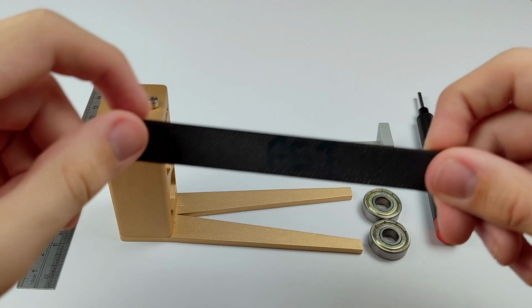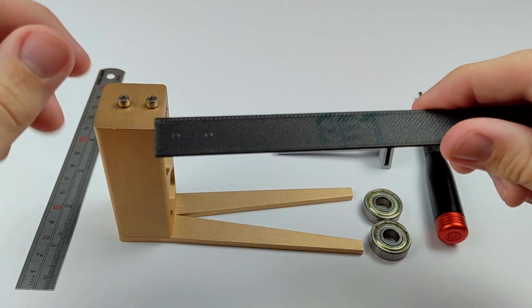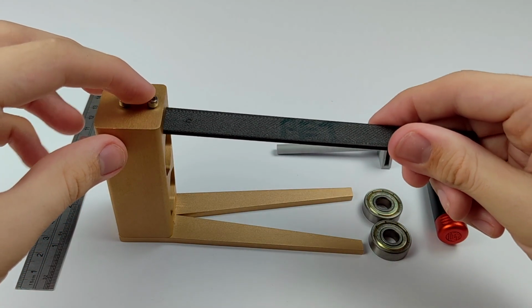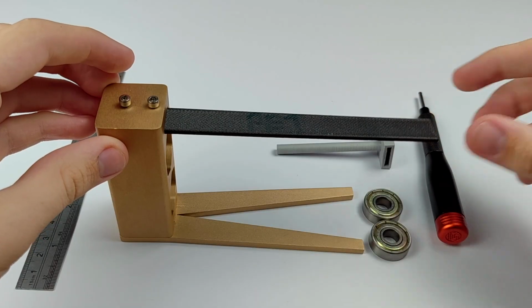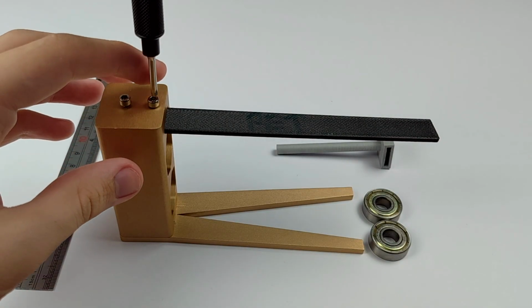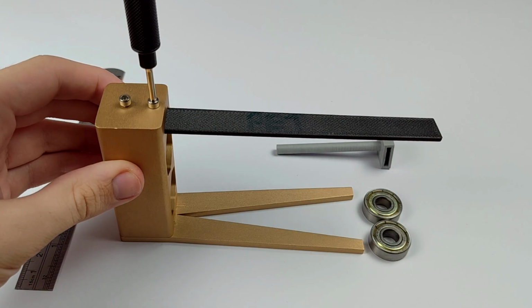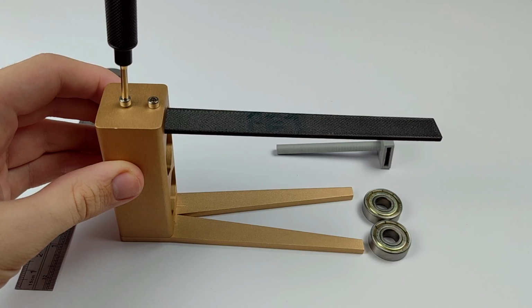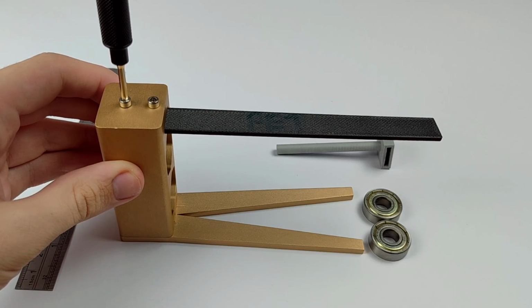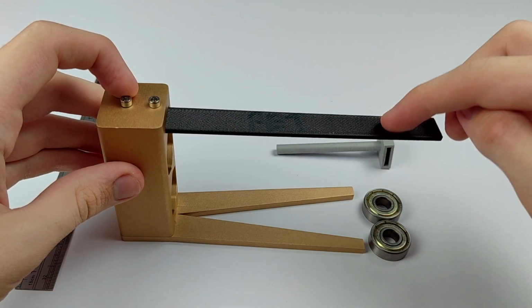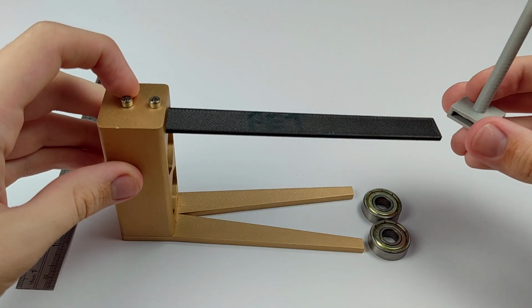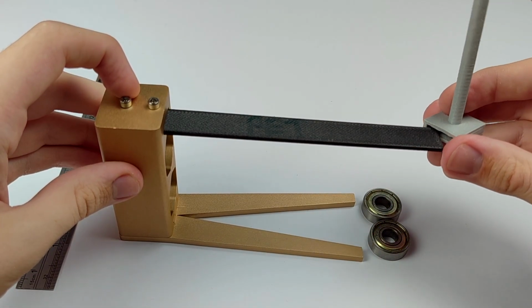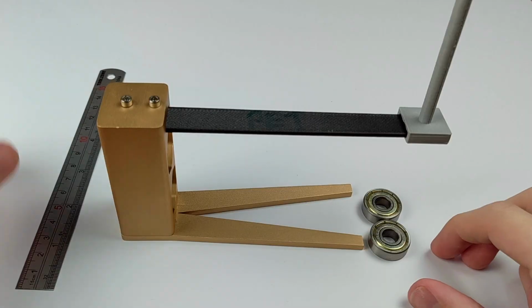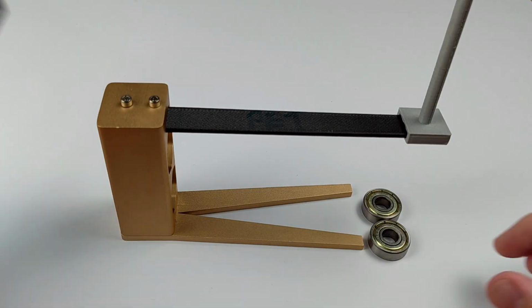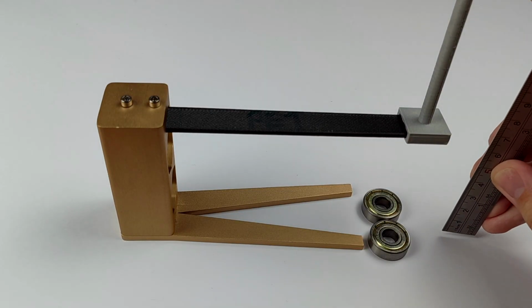Here's the process I'm using to test them, for which I'm using PET CF to demonstrate. First, I put the test strip into the slot and ensure it's pushed all the way to the back of the cavity, to ensure the lever arm is always the same for every material, before I clamp it in. Second, I put the weight holder onto the other end of the strip and measure the height from my desk to the front bottom corner of the holder, and record this as the zero position.